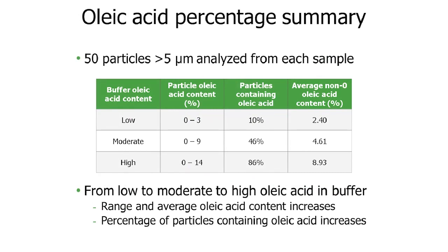Samples with low, moderate, and high oleic acid content in the buffer were analyzed in this way to determine if increased buffer oleic acid content caused increased particle oleic acid content. For each sample, 50 particles greater than 5 microns in size were analyzed. When the buffer had low oleic acid content, so did the particles. Only 10% of particles contained oleic acid, and of those 10%, they only contained up to 3% oleic acid.